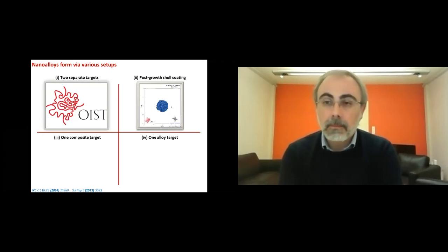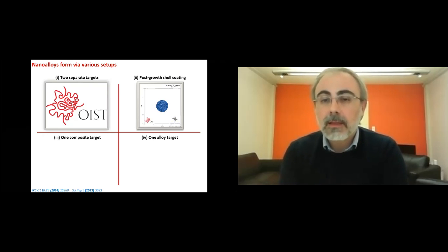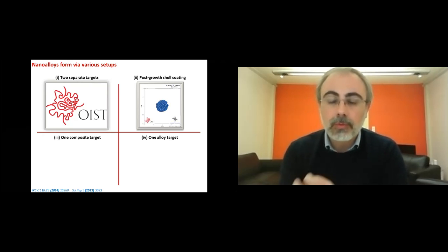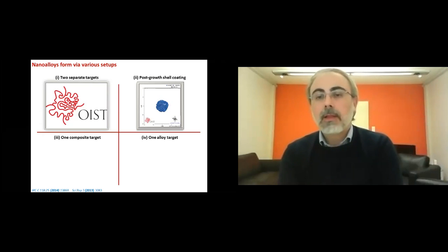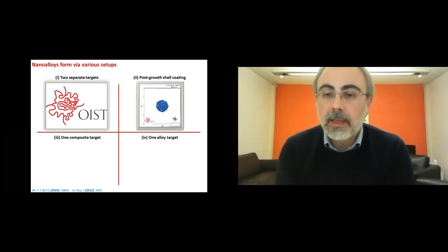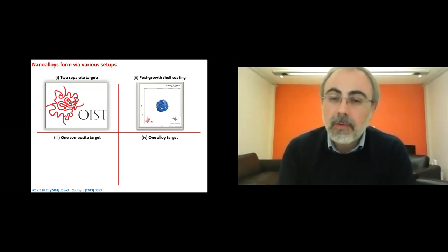And silver has a much lower surface energy than silicon, which means that the precipitates do not want to stay inside the silicon cluster, so they segregate to the surface. And as they do that, they actually induce crystallization for the silicon cluster. Initially, the silicon cluster was amorphous, and with this process, the silicon cluster crystallizes. And this is important because you can actually crystallize silicon clusters this way, even when they are too small to be crystalline by themselves.